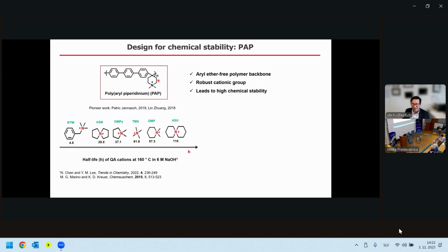Because people have done systematic studies looking at all kinds of cations in accelerated tests, their lifetime. If you have a benzylic one, we already said it's not really good. If you have 5-member cyclic bonds, it's also not so good. Tetramethyl actually is not bad. But if you have a piperidine, a 6-member ring, and even this spiro functionality, two 6-member rings, it is much more stable. And the reason for it is basically based on chemical structure considerations.